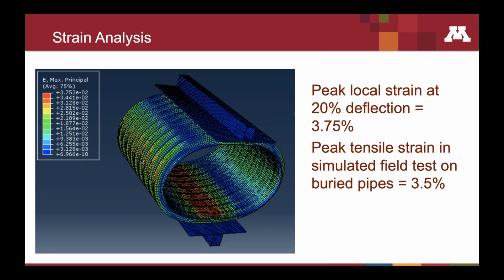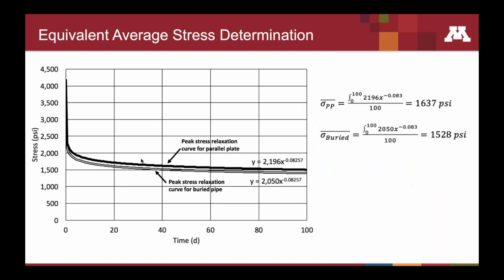This is some finite element modeling we did to assess how high the strains and stresses were in the pipe wall. And then basically we established some curves to come up with an average stress over the duration of the installed pipes. And we found that under these conditions, in that parallel plate test in the lab, we reached a stress of about 1,600 psi, which is again over 3 times what we had used for the service life prediction model. And in the buried pipes test, we made it to 1,528 psi.